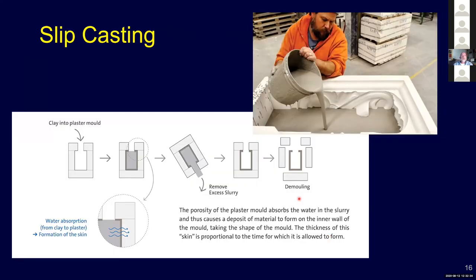Slip casting as a cartoon, if you will. Here's a worker who's casting for this shape. You can see the inside surface of the mold. He's casting the suspension in. What happens then is he casts it into the mold, in our little schematic here, and then water is absorbed into the surfaces of the mold and leaves the particles behind. When they get to the desired wall thickness, so they make these typically hollow, they can do solid castings as well, they're typically hollow, then they'll drain out the excess slurry, and that leaves you a wall of clay, basically.